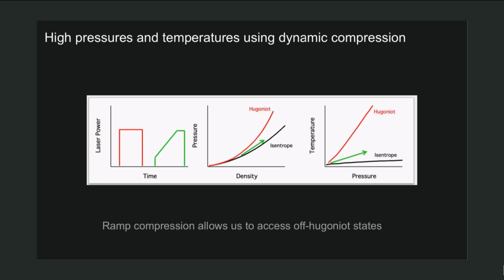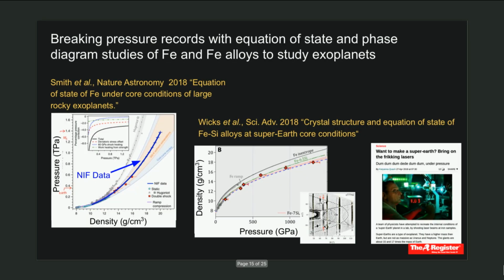And so we can go to higher pressures and measure conditions that are more similar to those of adiabats inside of a terrestrial planet, for example. But we can also explore the higher temperature side of the Hugoniot as well if we use a porous sample, for example. And so there are different ways to, again, tune where we can go into high pressure.